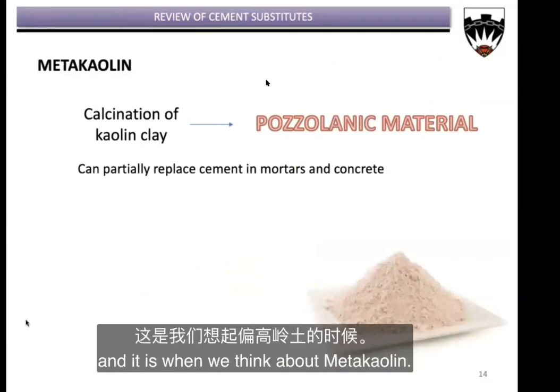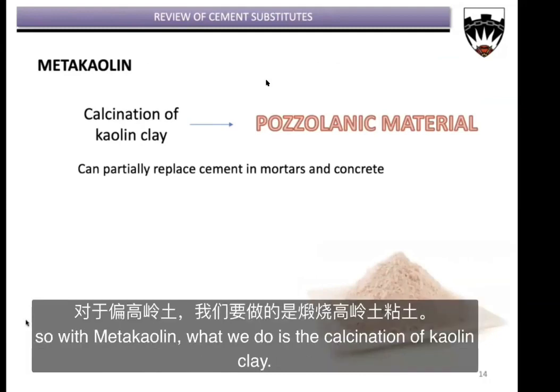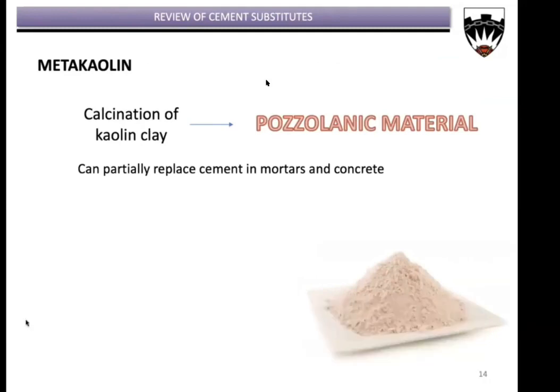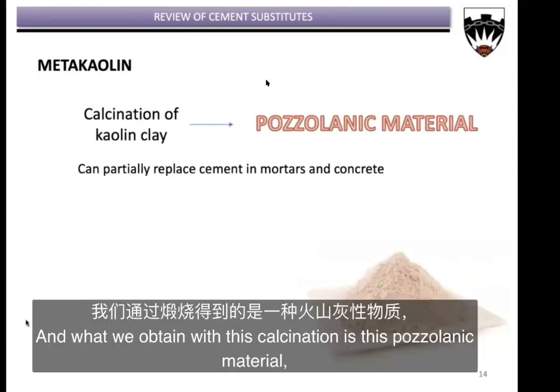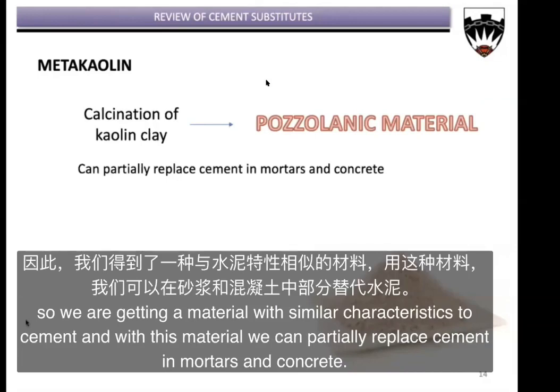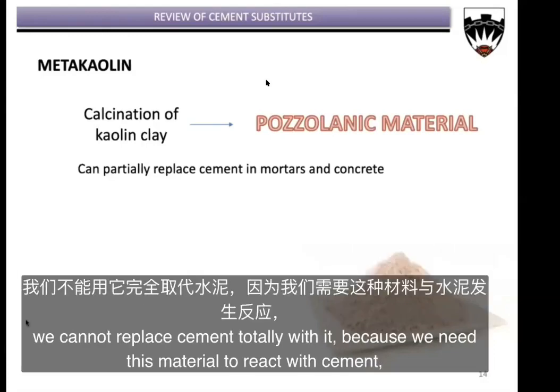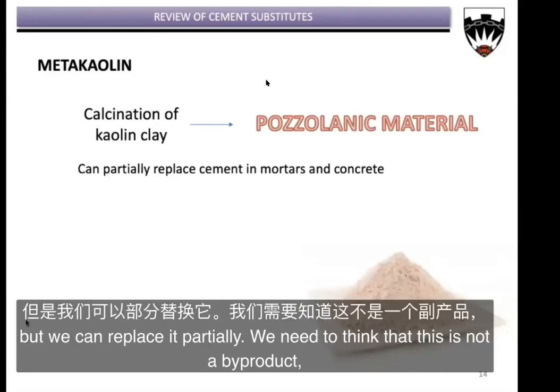And it is when we think about metakaolin. So with metakaolin, what we do is the calcination of kaolin clay. And what we obtain with this calcination is a pozzolanic material. So we are getting a material with similar characteristics to cement. And with this material, we can partially replace cement in mortars and concrete. So we cannot replace cement totally with it because we need this material to react with cement, but we can replace it partially.